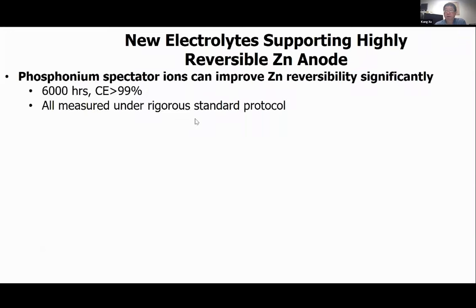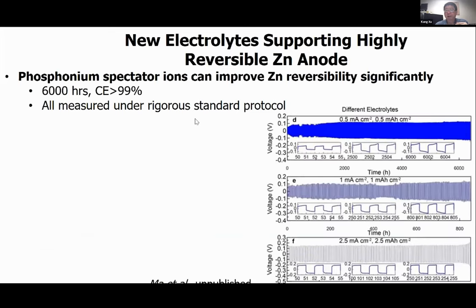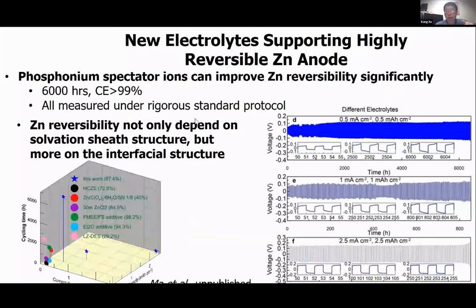So in developing our own electrolytes, we rigorously follow the protocol we established and suggest to the entire community. We found that by using one phosphonium spectator cation, which I mentioned already, we can reach coulombic efficiency up to 99%, and that can support reversible cycling of the cell up to 6,000 hours, which is about 3,000 cycles.